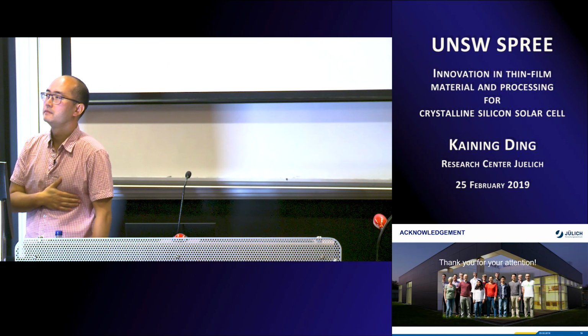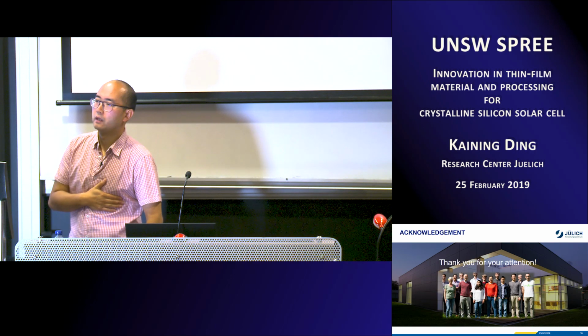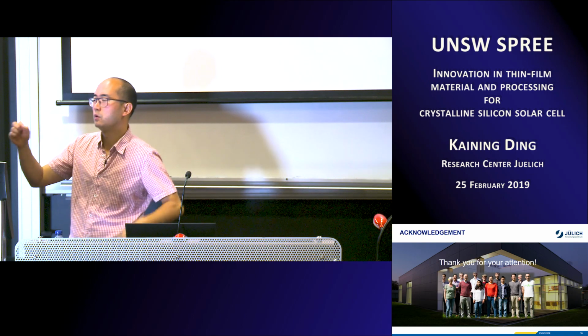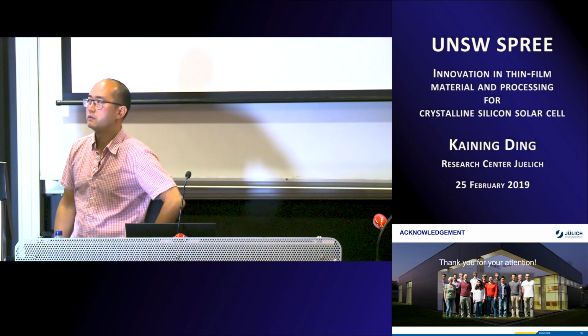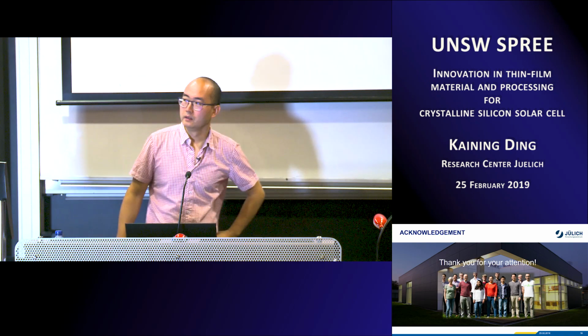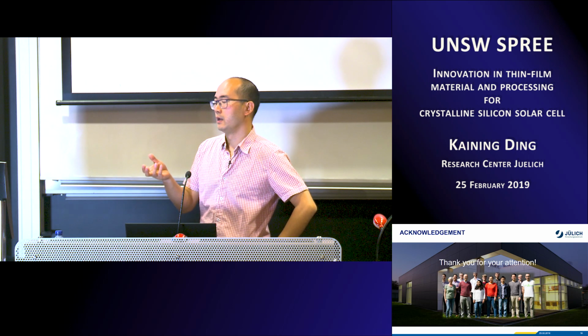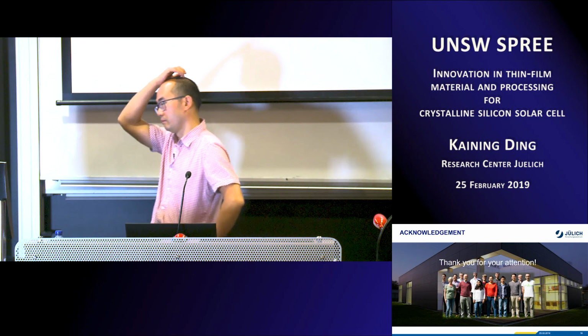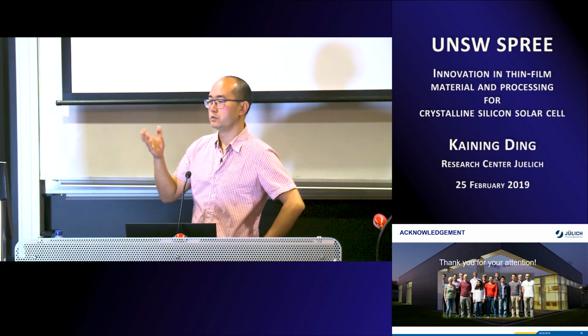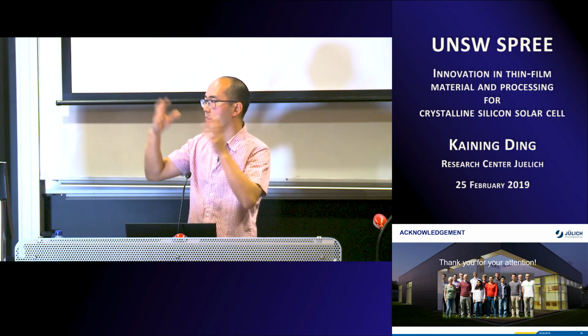What about the energy consumption of that machine? Because you're going to very high temperatures. You're avoiding the plasma and the ion surface bombardment, but then you're going to very high temperatures. Is that actually feasible? I'm not sure about that point, but you are only heating up the wires. I don't think it's too different from PECVD. You are not heating up the wafer, the substrate itself. The substrates have a substrate temperature, maybe kept at 100 or 200 degrees C, and the wires will increase the temperature on the substrate a little bit, like 50 or 100 degrees C. But you don't heat everything up to this high temperature.